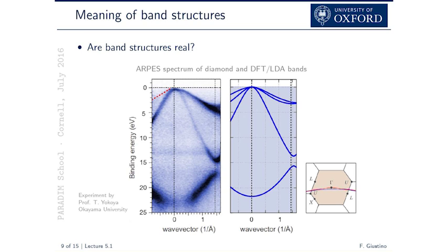The reason why in ARPES they need to do boron doping is that you cannot do measurements on an insulator, otherwise you have problems with charging. So the boron doping makes it into a metal basically, but the band structure doesn't change with respect to the standard insulating diamond. I mean, it doesn't change on this energy scale. It will change a little bit here.